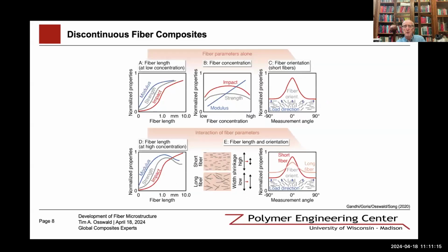So from a bird's eye view, I have these graphs. So the upper part is the fiber parameters alone. So fiber length has a huge impact on the properties. You can see, for example, the modulus, the strength, and the impact on the upper left side are all affected by fiber length. So fiber length is important. Fiber concentration is important. Of course, the impact strength eventually, you can see, reaches a maximum at a certain fiber concentration. Then it becomes more brittle. However, the modulus, of course, continues to increase with fiber concentration. And then fiber orientation, of course, plays a significant role in the final properties of the part.